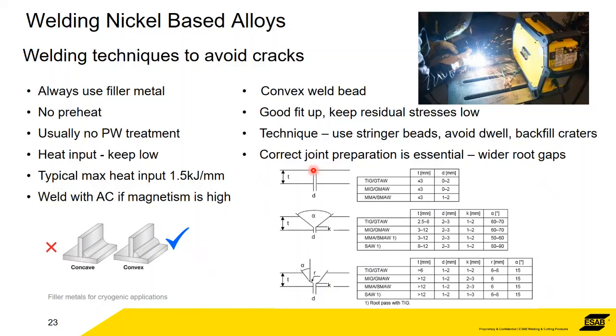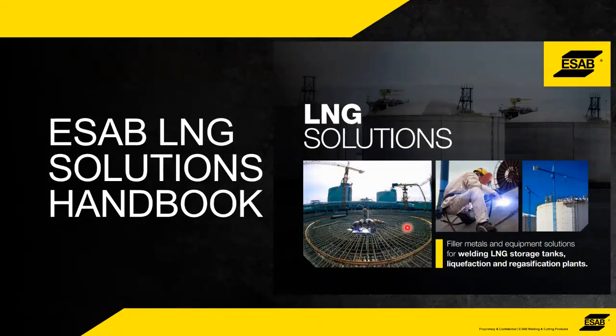So in order to ensure that you're getting flow and full joint penetration, full sidewall fusion, the joint has to be a little bit wider than you would normally expect for something like, say, a carbon steel. So the root gap needs to be wider and the angles need to be more open, whether it's a V, whether it's a J. And again, there are tables that we have to illustrate that.